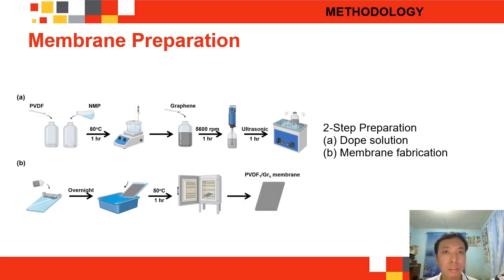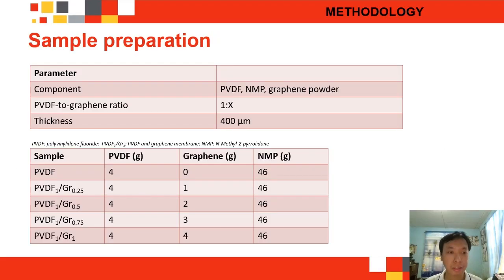And then, membrane fabrication. The mixture was cast onto a glass plate using a 400 micrometer casting knife. Then, immersed in DI water for 1 hour for phase separation. The membranes were dried at 50 degrees Celsius for 1 hour to remove residual solvent, producing the PVDF graphene membranes. A pristine PVDF membrane was also prepared without the graphene, with the same method. After that, there will be a total of 5 membranes prepared at the end of the fabrication process, with differing PVDF to graphene ratio. Also, all membranes have a thickness of 400 micrometers.